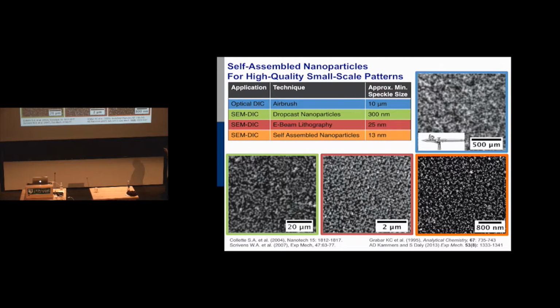If you're up at the macro scale, you can just airbrush it, and you can airbrush anything about 1 millimeter or more. You can just use an airbrush, like when you're painting shirts. We tried next actually doing E-beam lithography. The problem with that is, A, the image isn't very good. This actually isn't very random, and you need something that's very, very random in order to make the grayscale in the boxes unique enough for tracking.